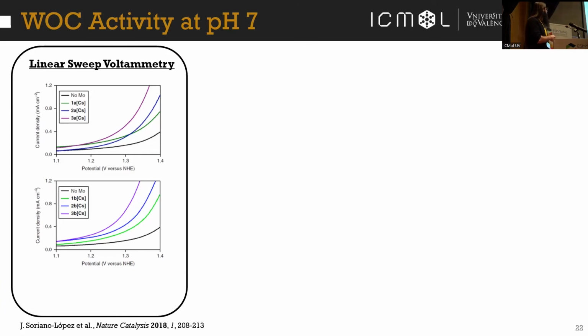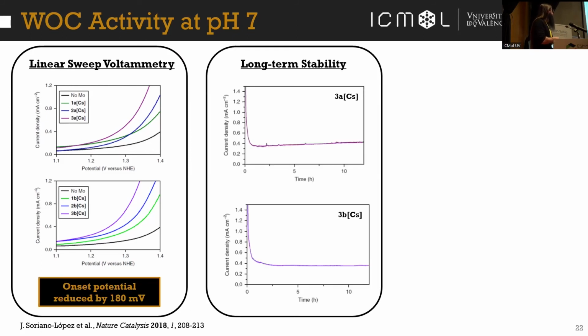And the first thing we did was linear sweep voltammetry, and we can see here that when we compare it with the parent cobalt-4 with no molybdenum in the structure, in both cases, increasing the amount of molybdenum in the crystal structure would increase the catalytic activity. So we could reduce the onset potential by 180 millivolts. And then we also tested the long-term stability of the most active crystals. We see that they are perfectly stable under these conditions.